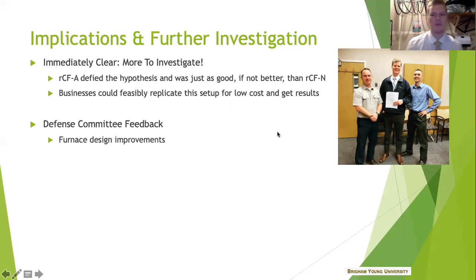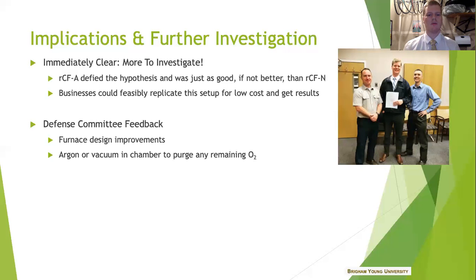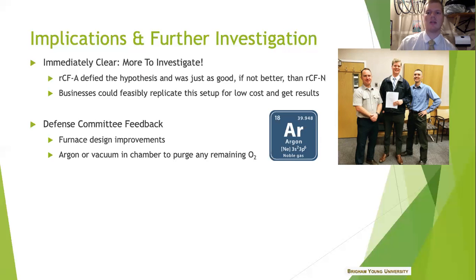They suggested that I actually improve the design of my furnace, my aluminum combustion chamber a little bit, to allow for argon to be plumbed into the chamber. And this is so that any remaining oxygen can be purged from the chamber. Of course, nitrogen has a lighter molecular weight than oxygen, so there's going to be a little bit left over on the bottom, and argon would sink to the bottom. It's heavier molecular weight than oxygen, so it would just purge that out. And I did think about that, but honestly, the argon tank was like twice as expensive as the nitrogen one. So that's the main reason why I didn't do it, but I need to maybe ask for some more funding for my next round so that I can have that.